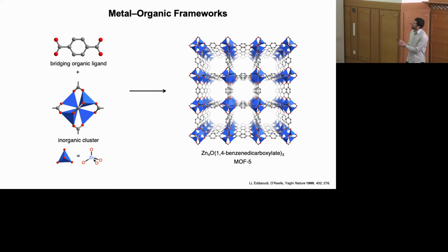And so if you could think about applying similar types of coordination chemistry principles, not to the ordered crystalline phase, but to the disordered amorphous or glassy phase, then you would have a lot of opportunities for being able to control the local structure of a glass in a much more predictable and tunable fashion than is possible in other types of materials. And also to think about controlling local distribution of void sizes and shapes within a glassy material.